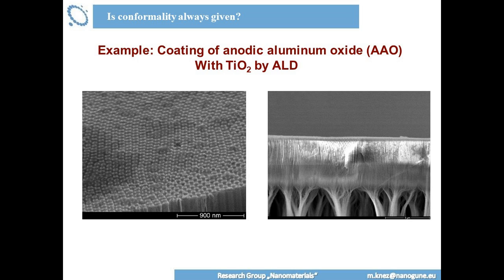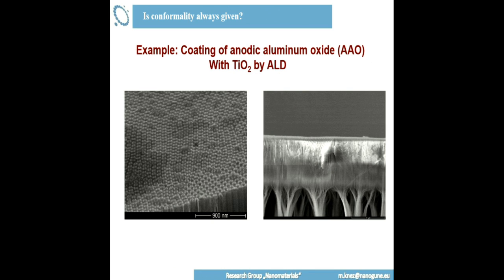In this case, it may not necessarily be the only case. With many processes, you have byproducts, byproducts during the ALD process which contaminate the surface behind. That means if the precursor comes in here and it adsorbs the next, second precursor, for example water, you produce isopropanol or you produce HCl. And those molecules, they are small, they can penetrate deeper and deposit beyond the coating. And they will contaminate the surface. That means the next titanium precursor will not be easily able to bind. And this happens very, very often, especially with titanium, we have this in many cases with isopropoxides and chlorides, depending, of course, on the substrate.